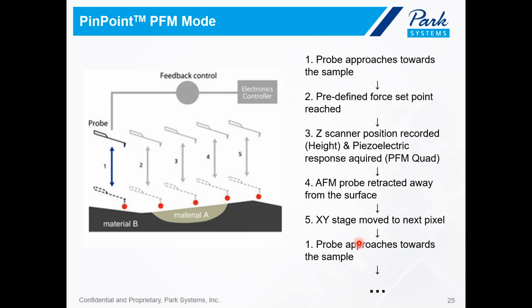Basically, in PinPoint PFM mode, the AFM probe monitors its feedback signal, first approaching the sample until a predefined force threshold value is reached, and then the Z-scanner position is measured, which will be our Z height signal. The probe will also stay in contact with the sample for a certain amount of time that can be defined by the user. This is for the piezoelectric response acquisition, including the PFM phase, PFM amplitude, and also the PFM Quad signal. After the signal acquisition is finished for both the height and the piezoelectric response, the AFM probe will be rapidly retracted away from the surface, again to a user-defined height.